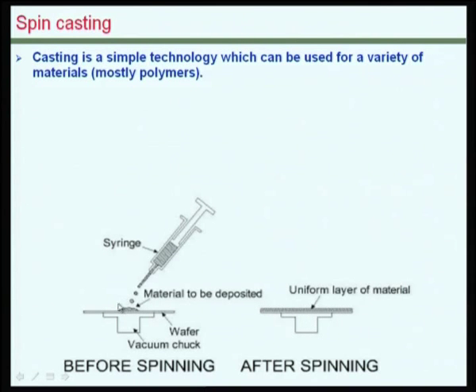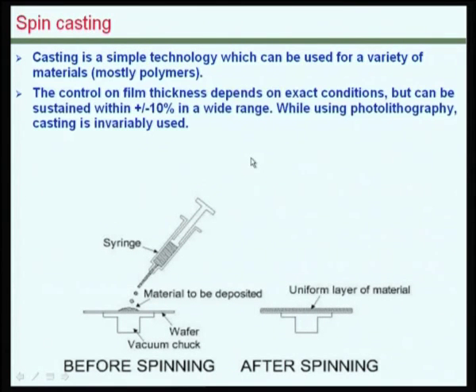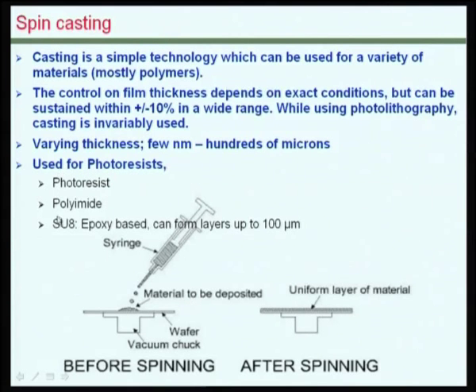So, when you are spinning, the droplets would be spread into a thin film based on the centrifugal force, and the surface tension and the rate of RPM are controlled basically to obtain various thickness films. A reasonably good uniformity of thickness can be obtained at a quick rate by this approach. There could be minor variations in the thickness though, and it is typically used for polymeric materials such as photoresist, polyimide, and even SU8, which is incidentally becoming a very common material for microsystems applications.